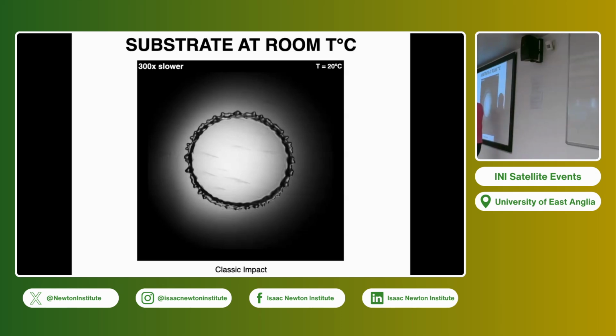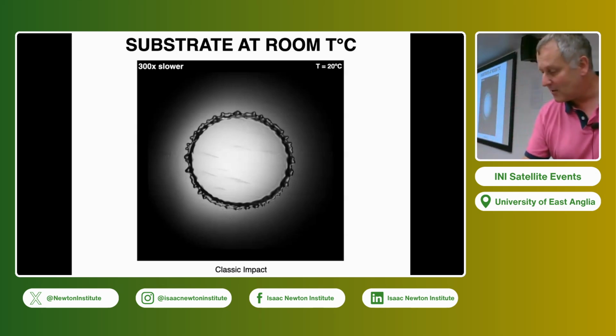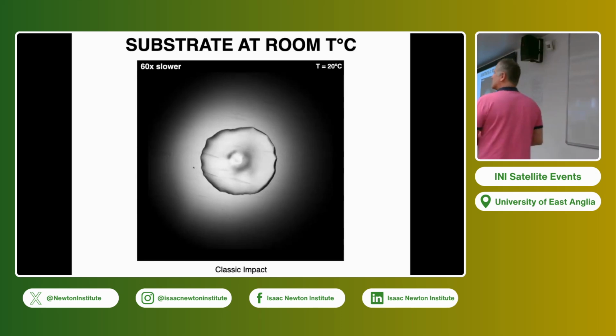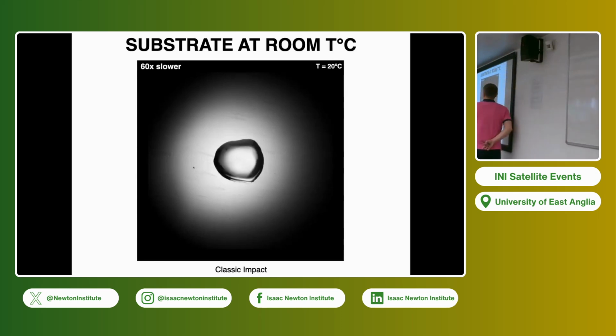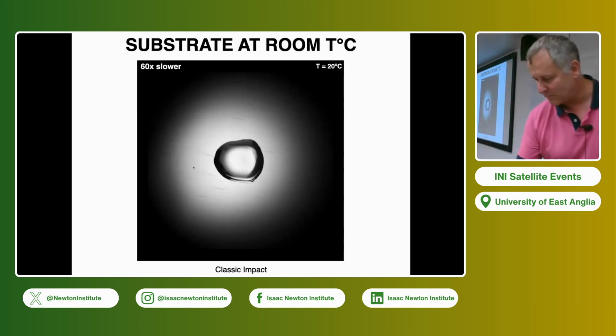You have a rim which is already a little bit corrugated, and you have a very thin film of liquid. We are at room temperature, nothing else can happen, so what happens? It retracts. It retracts because the contact angle of the water on this substrate is much different than the one corresponding to the maximum spreading diameter, so it has to retract because of surface tension. If we believe that there will be no defects on the surface, we would expect that it will retract as a circle. It does not exactly retract as a circle, but we always have some small defects on the surface.